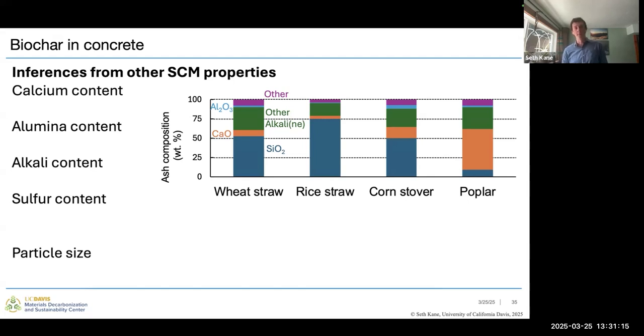And then finally, I've left this to the end because we can tune it a little bit, but it does require some energy inputs to do so. The particle size of our biochar should be pretty similar or a little bit smaller than the particle size of our cement particles to make sure that that's well distributed throughout the material.